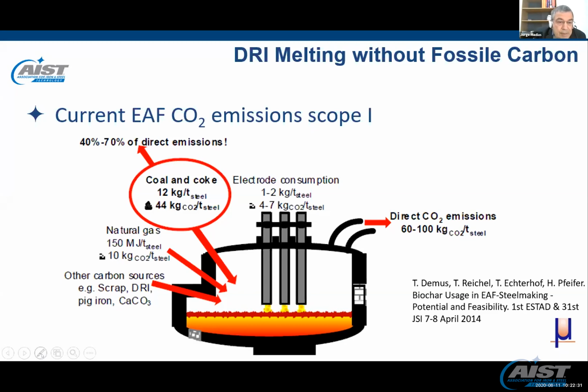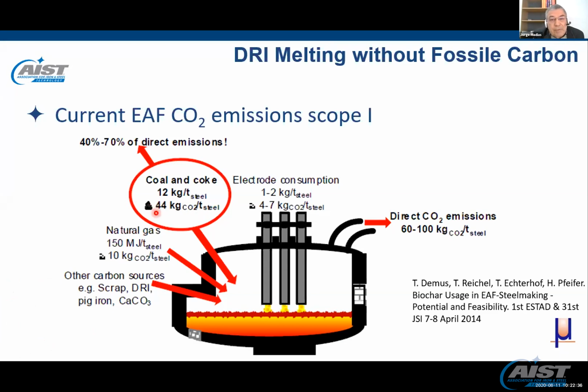regarding CO2 emissions. On average 44 kilograms of CO2 per metric ton of steel. Looking at carbon in the bucket and injected carbon, some 10 kilograms of CO2 per ton of steel from natural gas, and then 4 to 7 kilograms of CO2 per ton of steel coming from electrodes. Then we have, of course, other carbon sources such as scrap, DRI, pig iron, carbonates, etc.